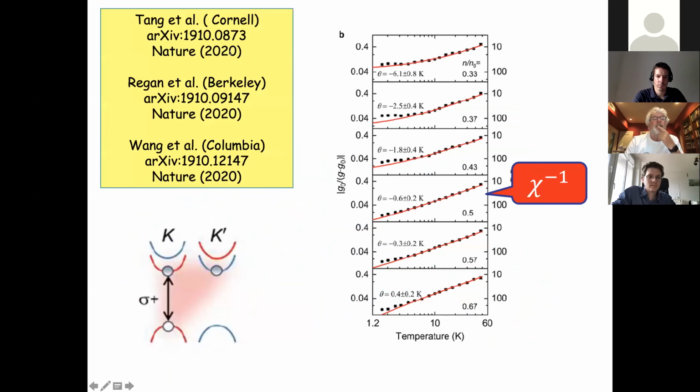These experiments, there are 3 first papers looking at strong correlation physics in this system, came out on the arXiv last fall. One of the interesting things that they see is Wigner crystal states, which are broken translational symmetry states, are very common and presumably obscured by disorder in real crystals that are often described by the Hubbard model. These are Wigner crystal states, let's say, where every 3rd site is occupied, for example.